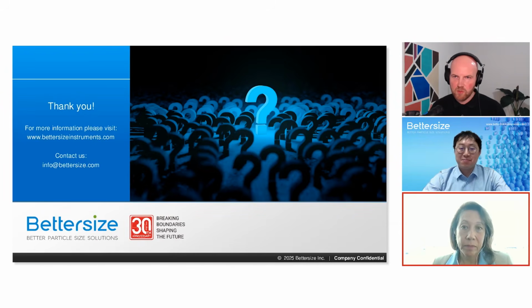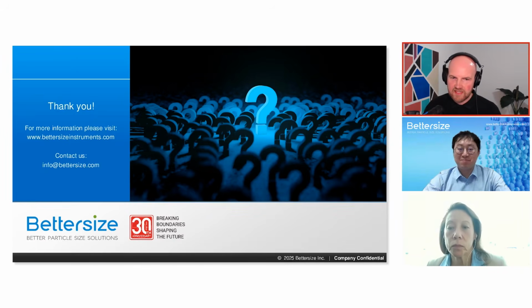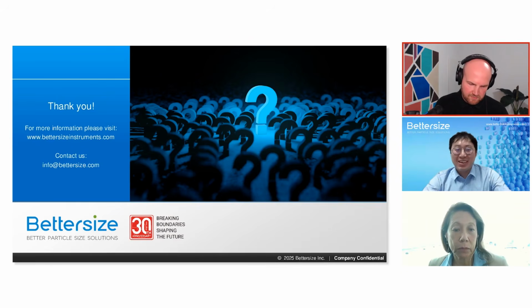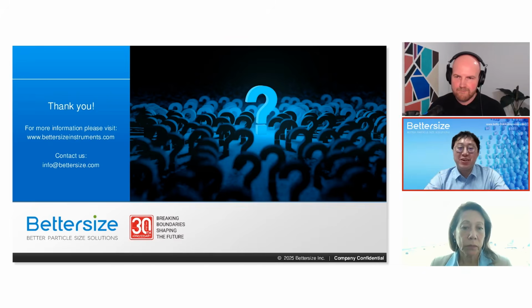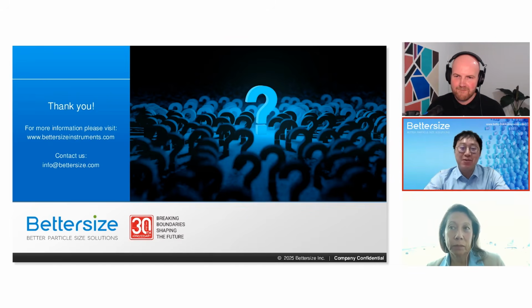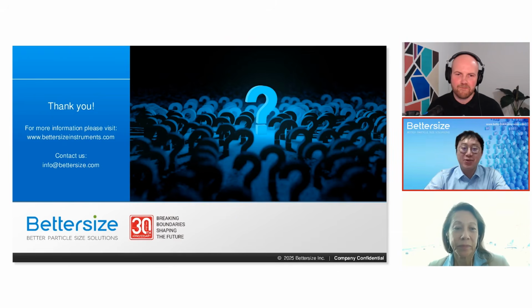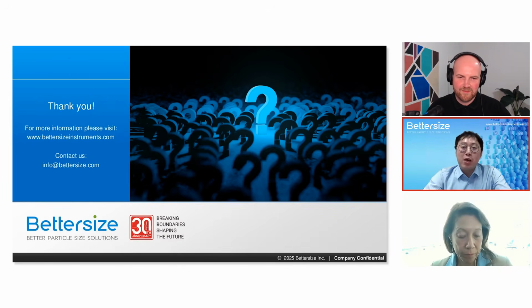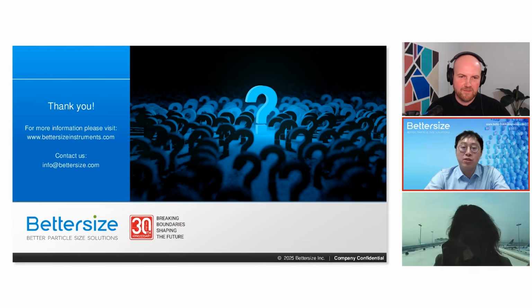Superb. Let's try and take a couple more. We're getting fairly close to the hour, but let's go to number 18 on our list. Up to what particle size does the Bettersize 2600 measure? This would be a very easy question, since the upper size limit of the Bettersize 2600 is 2600 microns. But one thing worth noting is that if we combine the Bettersize 2600 with a PIC1 image analysis module, the upper limit would be 3,500 microns. So this is it.